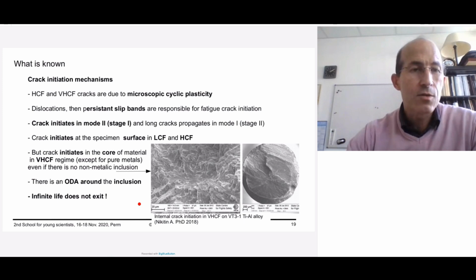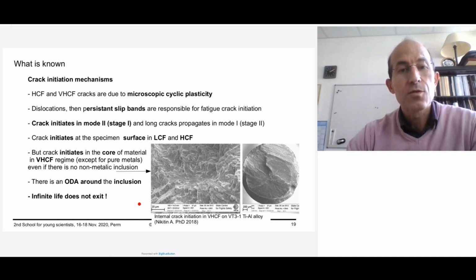So if I want to summarize what we know about crack initiation mechanisms, the high cycle fatigue failure and the very high cycle fatigue failure are due to microscopic cyclic plasticity. The dislocations and then the appearance of persistent slip bands at the surface of the alloy are responsible for these crack initiations. The initiation first starts in mode 2 of fracture mechanics. It means crack initiation is governed by shear, because shear governs microplasticity. And then the microcracks propagate up to long cracks and bifurcate when the crack length is large enough compared to the characteristic size of the microstructure, for then propagating in mode 1. This is stage 2 of crack propagation.